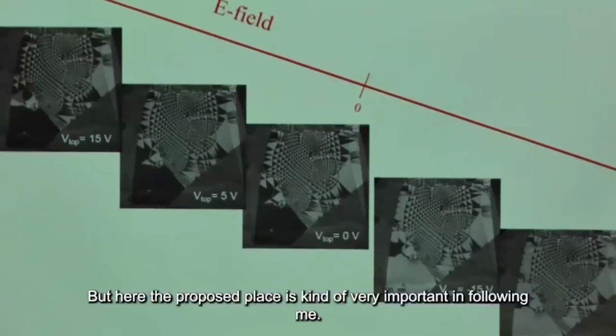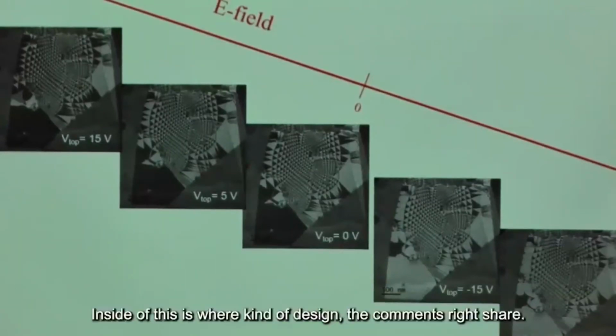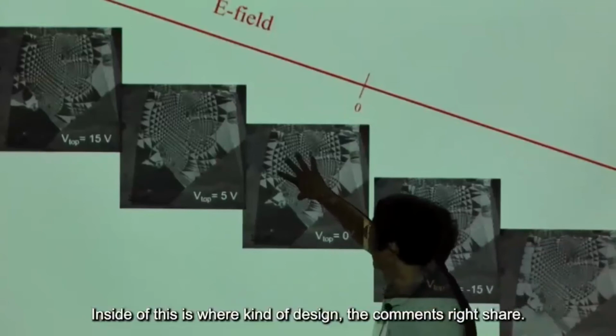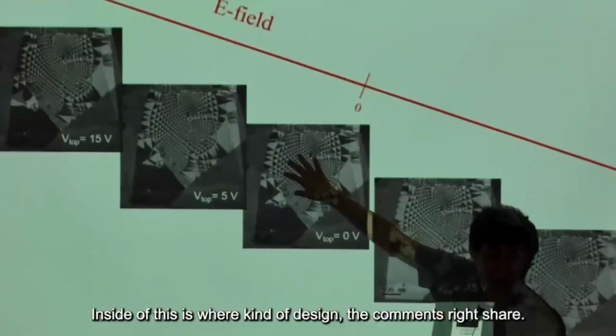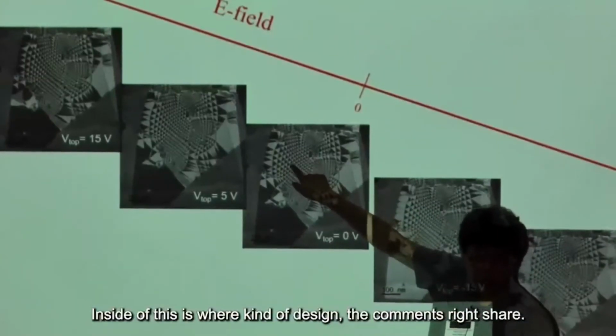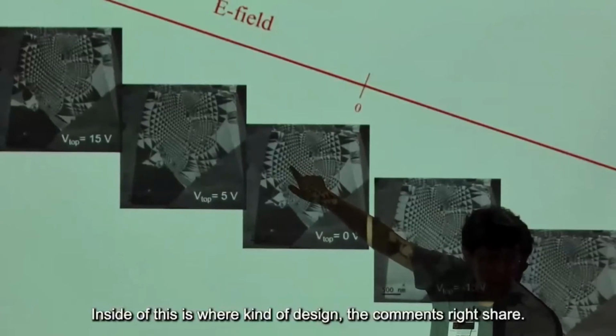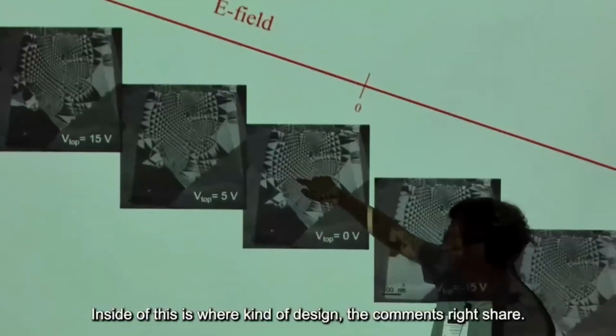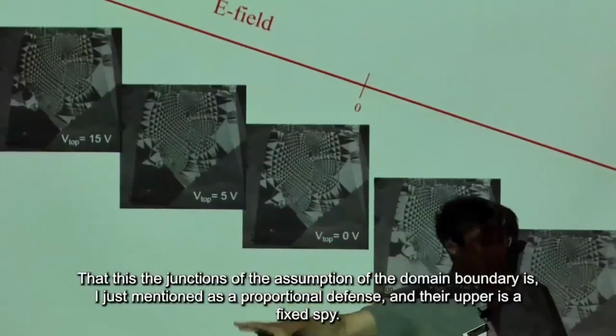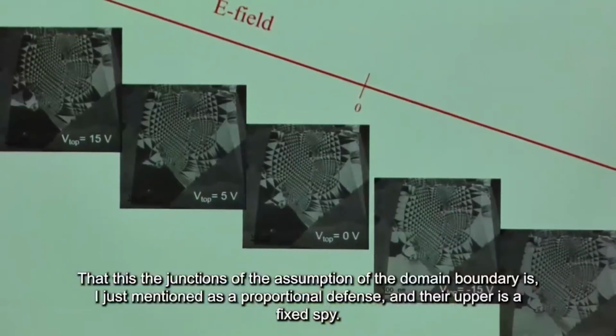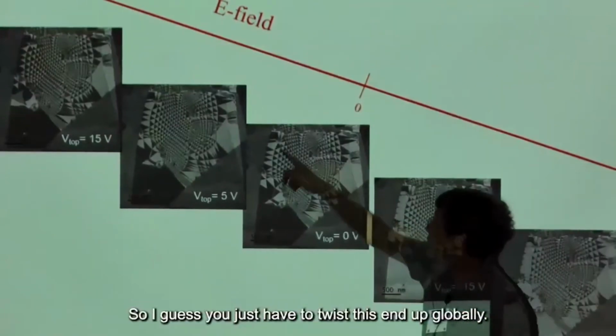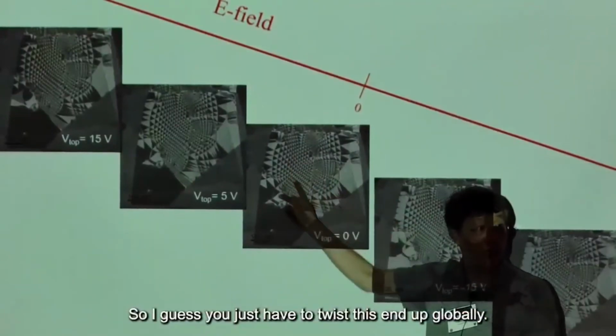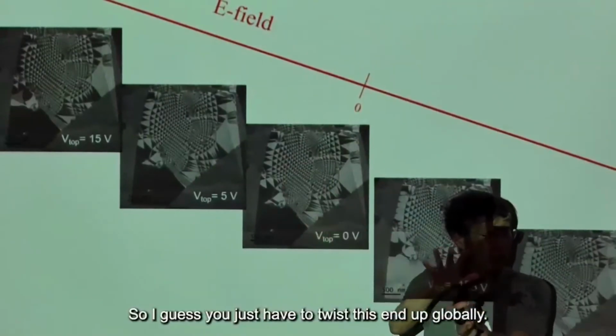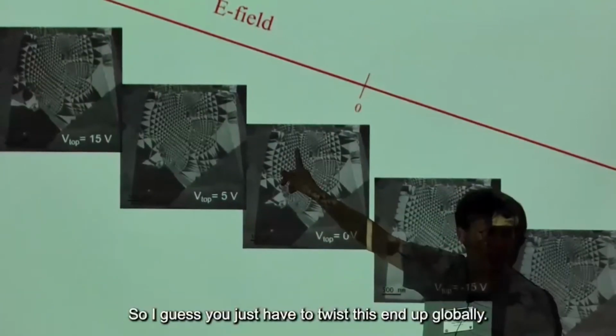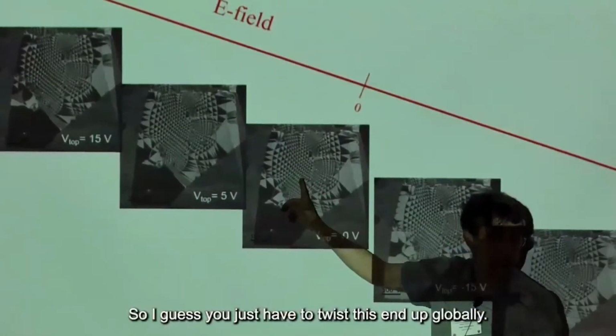But here the topology plays a very important role in the following way. Here, the junctions of the domains, or junctions of the domain boundary, are, as I just mentioned, topological defects, and their number is fixed by the average twist angle. So unless you twist this angle globally, I cannot get rid of any single one of the junctions inside.